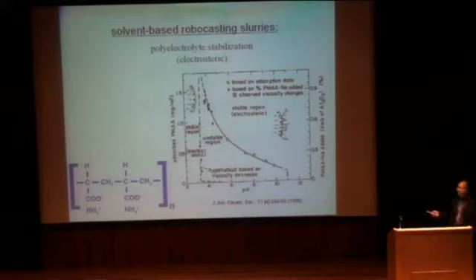One of the possible ways to get there is by using what's called polyelectrolyte stabilization. So imagine this is the surface of some ceramic particle. We put these little fuzzy, highly charged molecules on the surface. We absorb them on there. And now this becomes a barrier where we can control the repulsive force between neighboring particles. And this is what my graduate research was on, in that paper that Bill was talking about, that apparently is used quite often in ceramic processing classes. So back in 1988, somehow this paper gained some traction, and it's very rewarding to know that it's being used in classes here and in classes around the world.